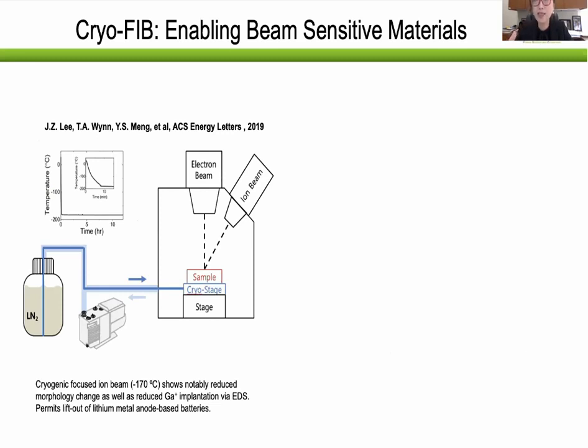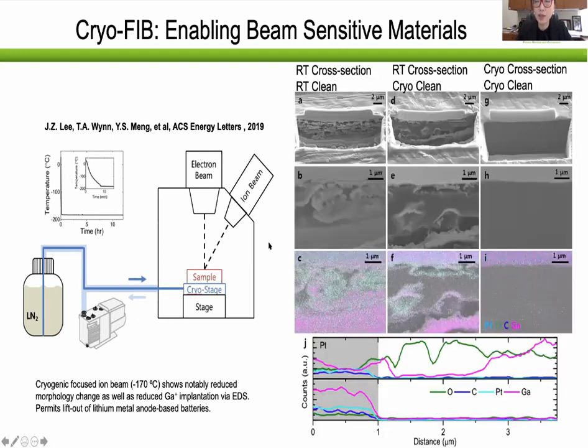When we say everything, it means everything, okay? So lithium reacts with oxygen, nitrogen, reacts with CO2, water, and it can alloy with many, many metals. One of the things we first discovered, why it is so important to have the right tool to look at the lithium, is because one of the tools we have, called the focus ion beam, uses gallium to cut the cross-section of the lithium. And then when we use the room temperature cross-section view, we found that this lithium alloys with the ion source, the gallium. So everything we measured here is the lithium gallium alloy instead of the pure lithium metal.